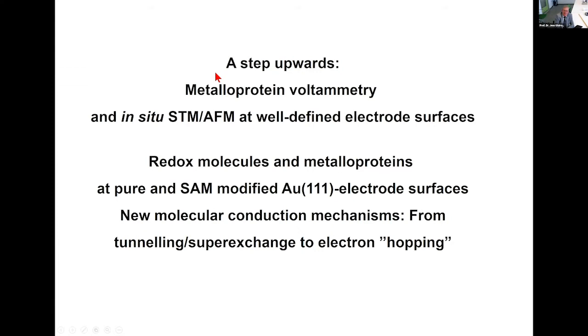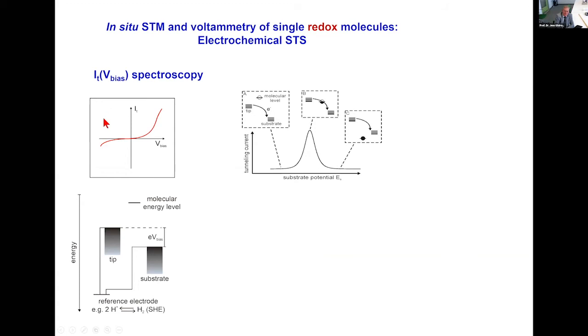Then we go a step upwards, you could say, to more complex molecules: metalloprotein voltammetry at the single molecule level, and in situ scanning tunneling microscopy and atomic force microscopy. Now this is no longer simply a tunneling mechanism. For a redox molecule, we have for scanning tunneling microscopy a tip and a substrate, and then there's a bias voltage that shifts the two Fermi levels by the bias voltage energy. For molecules in general, there will be a molecular level, the highest occupied or the lowest unoccupied molecular orbital.